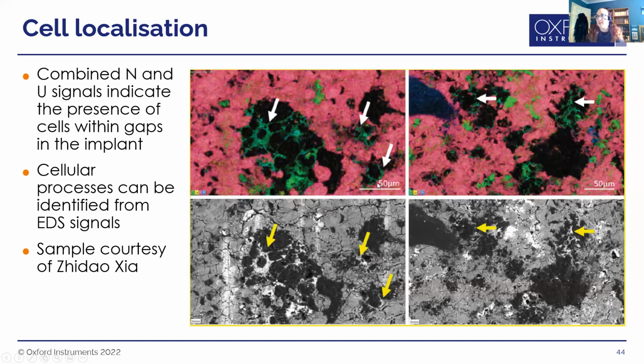So you can see in the EDS maps these areas where you get the nitrogen and the uranium signals overlapping each other, so you can positively identify that as cellular material. I would be less convinced about identifying that purely on the backscattered data alone. And likewise, when we move over here, even though we've got those stain in the regions, it's really difficult to pick out the biological material. And when you look at the EDS maps and you're able to resolve the different X-ray signals, you can really see where you've got all these really fine processes.